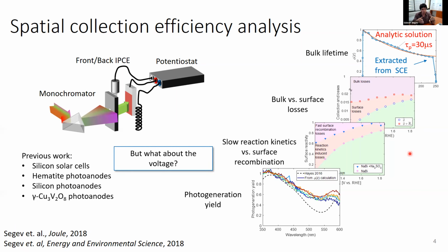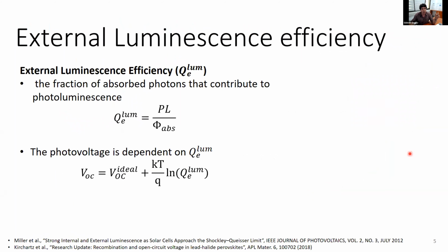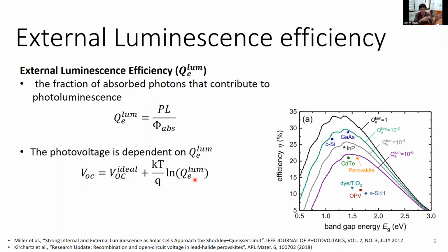The way that we tackle understanding contribution to photovoltage is actually passing through luminescence and external luminescence efficiency, or the photoluminescence quantum yield. There are tons of different names for this. The idea is it's the fraction of photons that are re-emitted in photoluminescence out of the device, and it was shown that the open circuit voltage is tightly connected to this number. The reason is that photovoltage is determined by quasi-Fermi level separation, but also radiative recombination. So these are tightly coupled, and we can actually calculate an equivalent to the Shockley-Queisser limit that is reduced as you reduce the photoluminescence quantum yield or the external luminescence efficiency of the device.